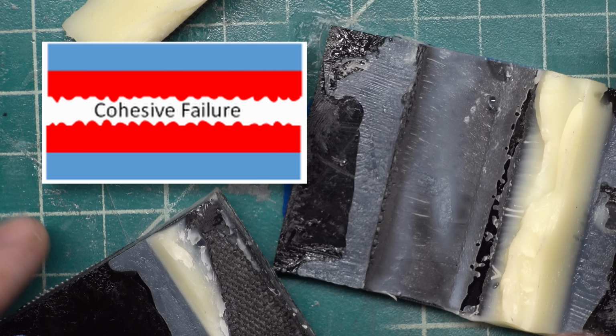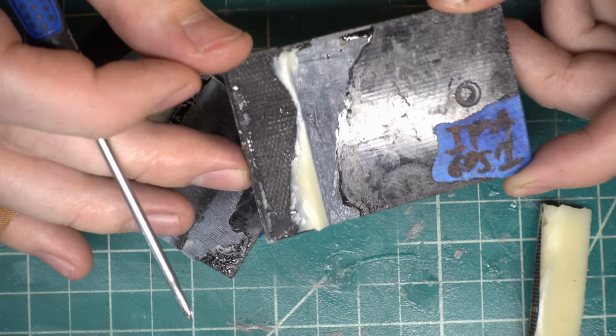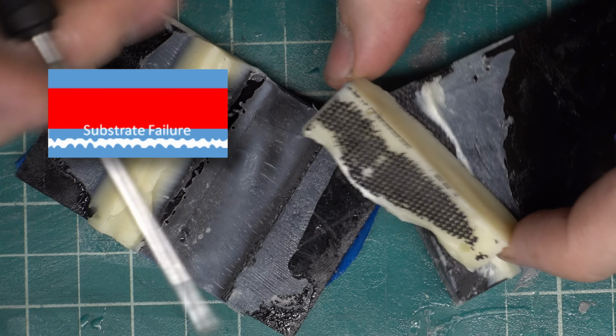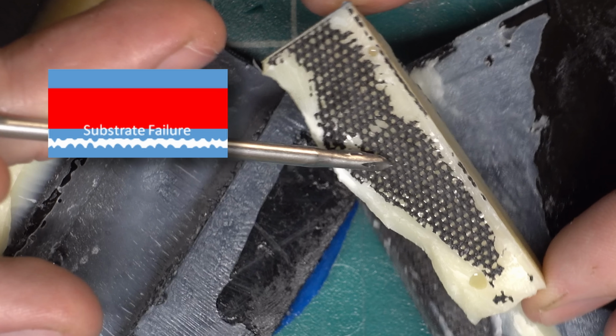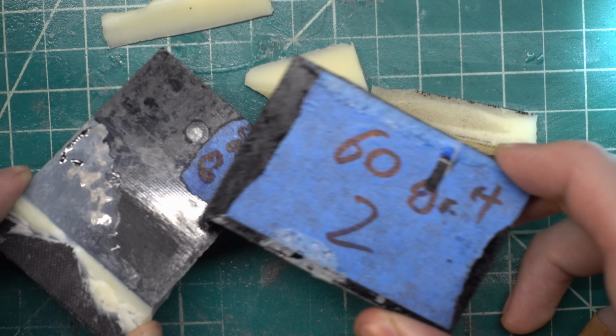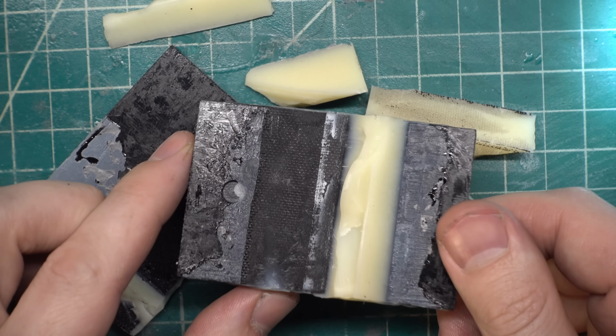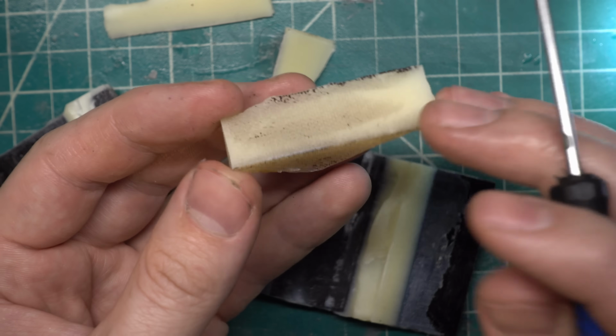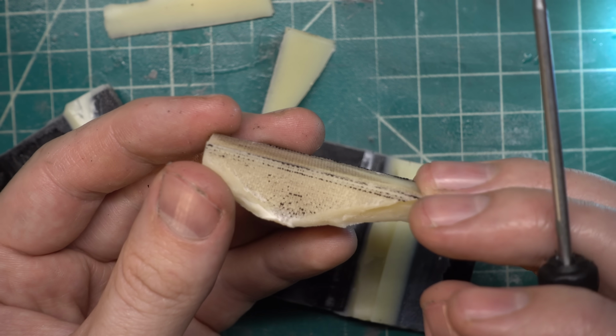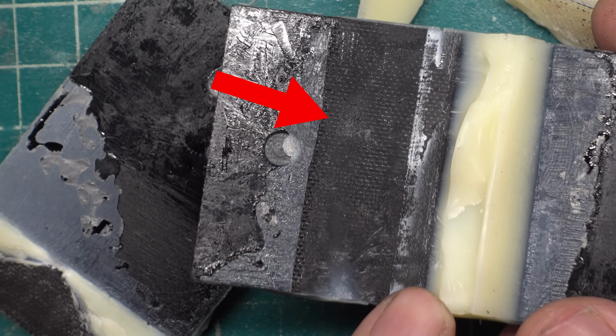This is a cohesive failure, which means the epoxy itself broke and it left a little bit on the surface. And on the other piece from this sample, we have a substrate failure. That means the structural epoxy ripped off the top layer of the substrate, or the resin on the fiberglass. For the 60 grit sample, we can see a combination of these two. The epoxy shards are tearing away some of the surface resin from the fiberglass, and there's also still a little epoxy on the surface.